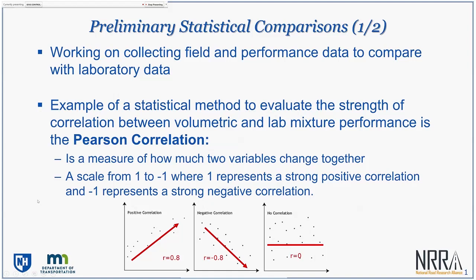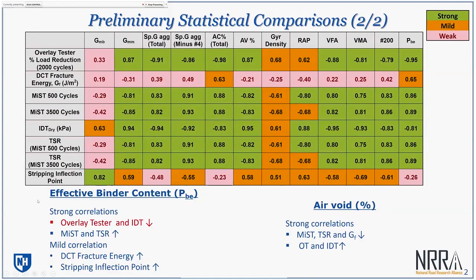These are very early results. I don't want you to really get bogged down on all these numbers on the slide. I'll just focus on some of the key points at the bottom of the slide. If we look at effective binder content, as this property increases, what we are seeing is that in general, overlay tester results and indirect tensile strength, again ITS at 25C from TSR, not the Superpave IDT at low temperature, are decreasing.